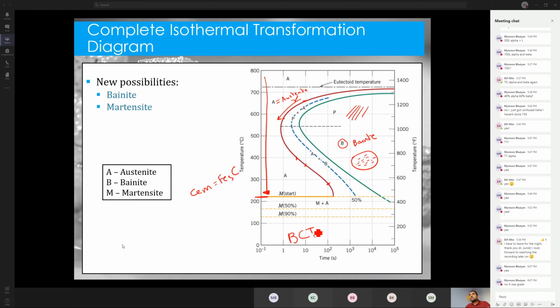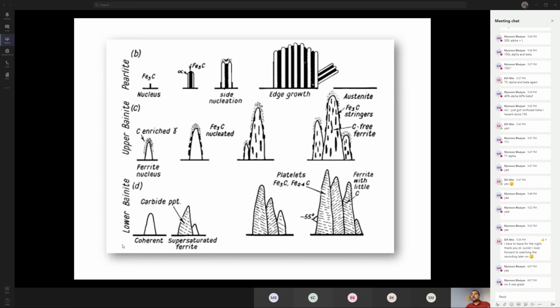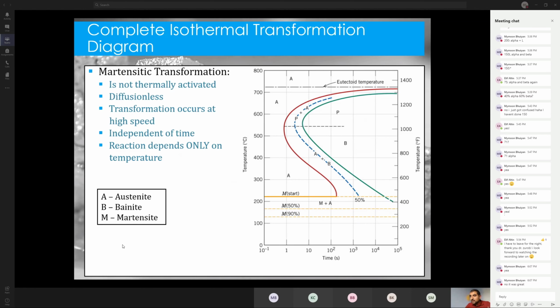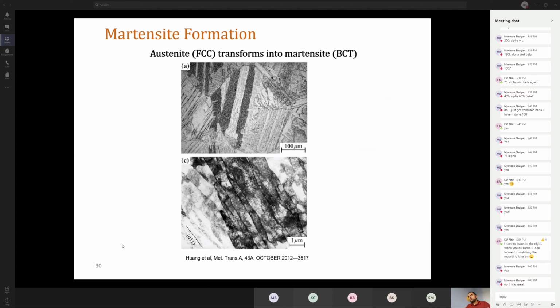So that shows you that depending on what path you take as you cool the sample down, maybe you make pearlite, maybe you make bainite, or maybe you make martensite. And this is just a schematic showing how these different ones look like. The top is pearlite, see the alternating lamella. The next two are two kinds of bainite, where you have the ferrite and some needles of Fe3C inside it. And then you have the martensite, which is this very messy structure you see here. This messy structure here, full of dislocations, full of deformation. This is called martensite.